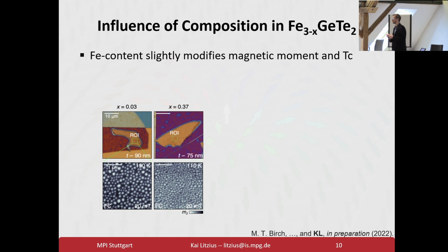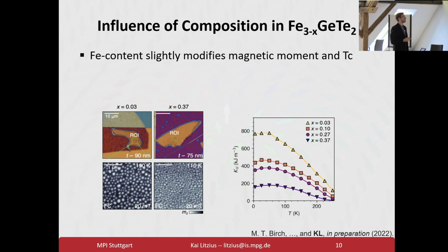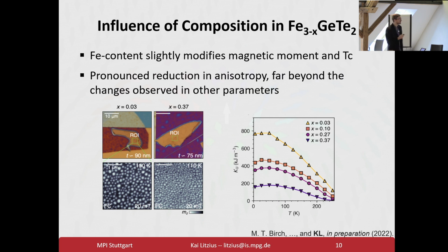What it actually does is quite significantly change the anisotropy in the system. And we're not quite sure what exact mechanism is behind that, but it seems to be the coupling between the van der Waals layers that causes this behavior. It actually changes the anisotropy by up to a factor of 4. So this is quite a significant change compared to only a few percent that we see in saturation magnetization or TC. So this is actually an option to tailor your magnetic system into a desired state, for example, more stripe-like, more skyrmion-like, and so on. So with this, we have a handle on what kind of state we want to be in, depending on what history the sample was put through before.